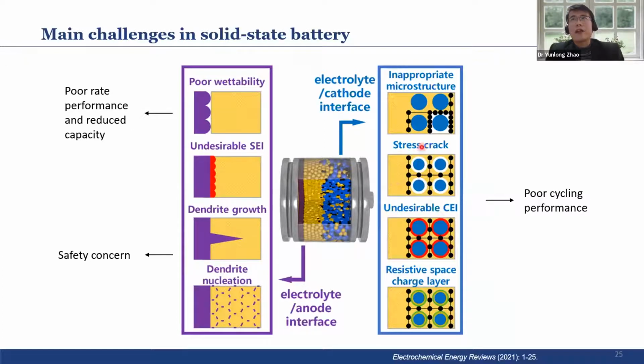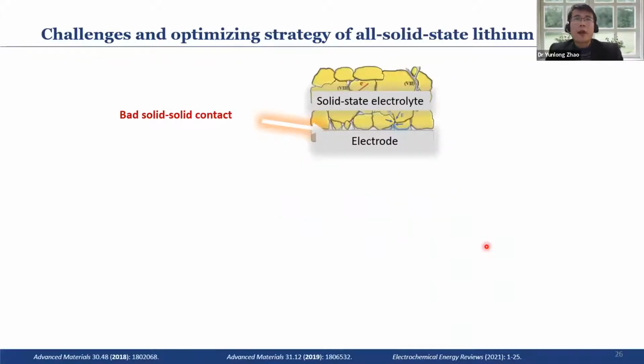On the cathode side, there is some strain cracking, and this is the cathode electrolyte interface. Similar to the SEI, we call it CEI. Those issues are generated at the interface and could lead to poor rate performance, reduced cycling performance, and also safety concerns. Because of the time limit, I can't go through them one by one. I will just pick several of the most serious issues and explain the reasons as well as how to solve these problems. So the first one is solid-solid contact.